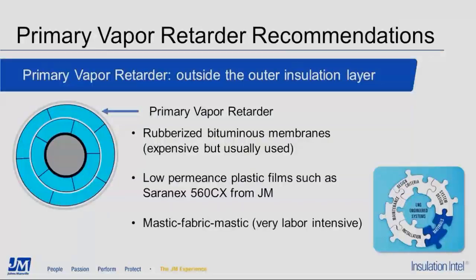In general, there are some specific materials that are recommended for use as vapor retarders in LNG pipe insulation applications. For the primary vapor retarder, the three most commonly used and recommended materials are rubberized membranes, which are expensive but are the most commonly used materials; low permeance plastic films like our Saranex 560CX, but there are other types of plastic films as well; and mastic fabric mastic, which is a very labor-intensive material and relies very heavily on the skill of the installer to achieve the desired thickness, because without the proper thickness, mastic fabric mastic will not yield the correct performance. And thickness is solely dependent upon the application.